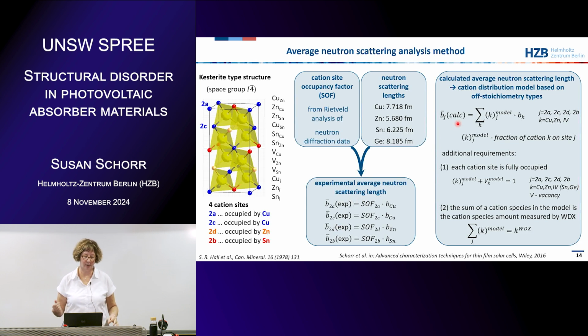Now you may say, okay, you have 4 cations, 4 sites, couldn't you do that forever? That's why we have 2 additional requirements. We assume that each cation site is fully occupied by the different cations and the vacancies. And because we know what we have in our sample, we measure the chemical composition by wavelength dispersive X-ray spectroscopy, grain by grain. So we know how many cation species we have, and we can only distribute what we have. We cannot distribute more, of course. So these 2 additional requirements also have to be fulfilled.